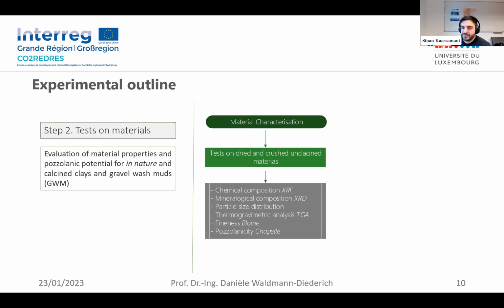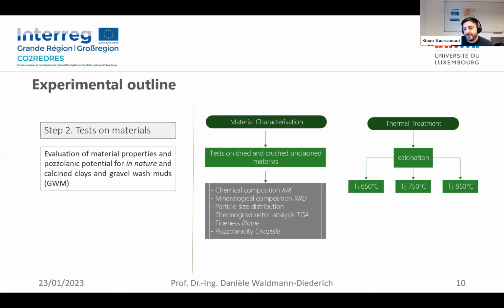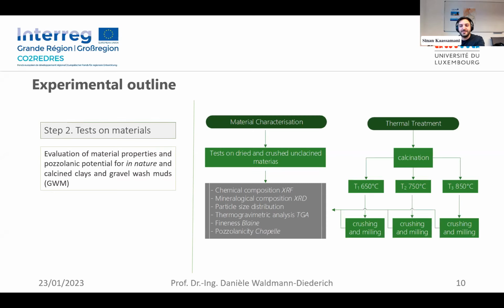For instance, in chemical composition, we want, of course, materials that are rich in silica and alumina, right? For the mineralogical composition, we wanted to see which clay minerals are there. Is it majorly kaolinite, illite, is there too much quartz, right? As well with the TGA, thermogravimetric analysis, we can measure where we have the peaks, right? So exothermal peaks, and where the dehydroxylation is actually happening. And then we treated these materials. So first we studied them, and then we treated them thermally, right? So we calcined them at 3 different temperatures, crushed and ground again.